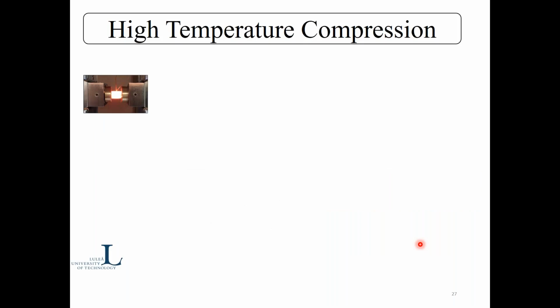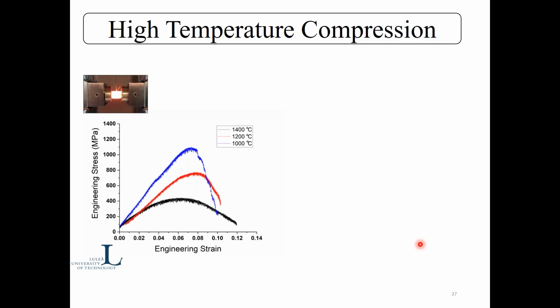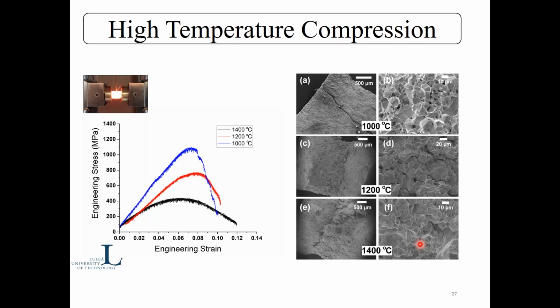Then to investigate the high temperature properties, we tested at 1000 degrees centigrade, 1200, and 1400 degrees centigrade. And we performed this test, and we got very good mechanical properties for this material. That means it can be used for very demanding applications up to 1400 degrees centigrade. So these are the fracture surfaces that we got. Different mechanisms were operative at 1000, 1200, and 1400 degrees centigrade.